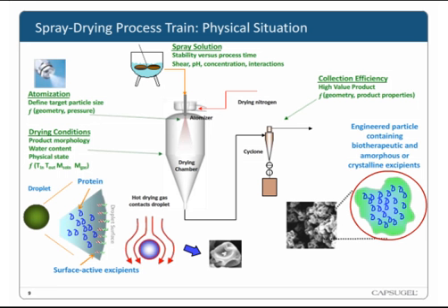And then the particle size that we're making here is often the type of thing that in a normal spray drying process, say for oral consumption, would just go through a normal cyclone. And so we've had to do some modifications to our cyclone to be able to enable high efficiency collection of these very small, very aerosolizable powders. And at the end, we end up with these shriveled raisin-looking particles that are in the range of 1 to 5 microns with a very tight span, as you'll see from the characterization data coming up.